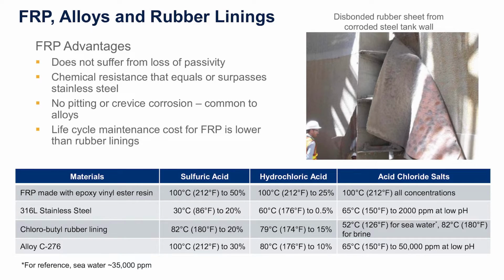So as you look at FRP and corrosion performance versus alloys, really what this slide is telling you, the take-home message, is that acid chlorides, acids really are something that FRP made with epoxy vinyl ester resins handle quite well, much better than something like a 316 or an HC276. And so at the end of the day, that's the reason why FRP materials really have become the material of choice for acid chloride type environments. Another area that you'll see is where rubber linings might be used in place of an FRP type material.